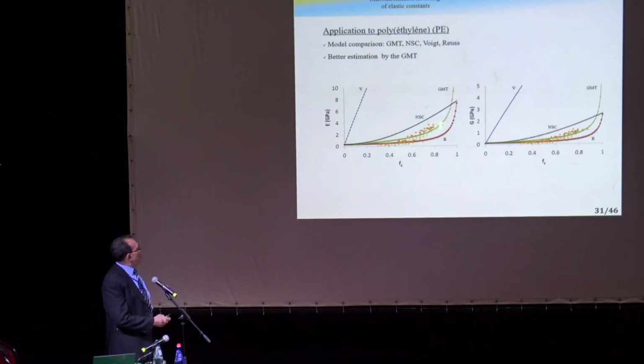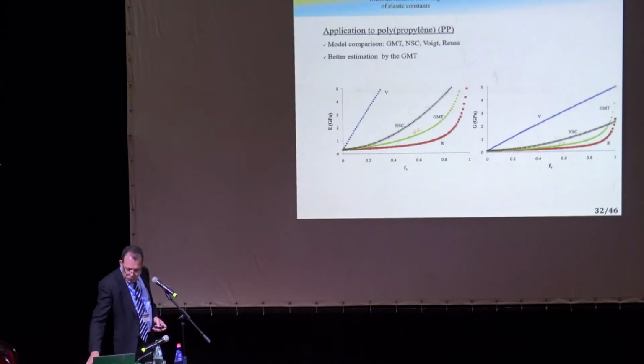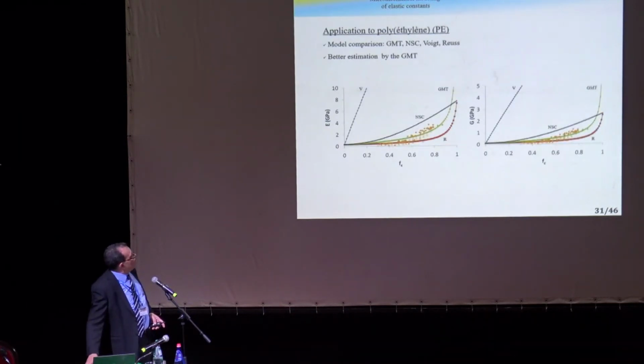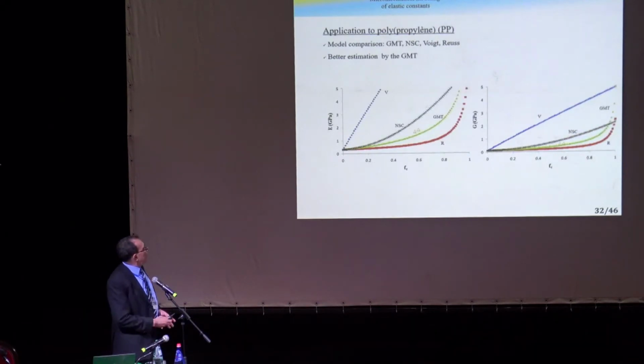And this is some experimental work. It looks like the generalized Mori-Tanaka gives us some nice results in this case. The same thing for the first one, which was polyethylene, and this one is for polypropylene. Same trend somehow, and we didn't have many experimental results to compare to, but we had only these two points.